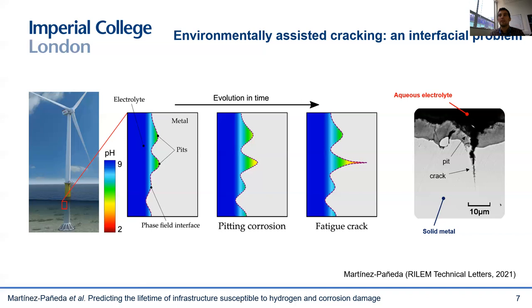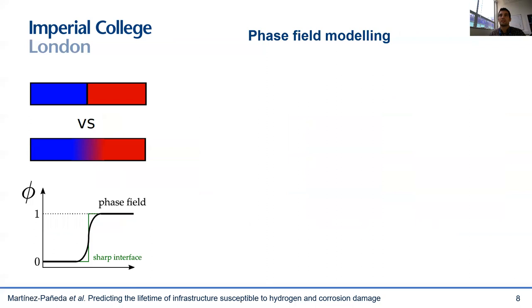The problem is that tracking evolving interfaces is a well-known mathematical and computational challenge. The good news is that a paradigm has been proposed that makes the tracking of interfaces an easy task. This is the so-called phase field method, which goes back all the way to van der Waals, but only recently has really taken off with the help of computers. Mathematically, we have two ways of dealing with interfaces: treating the interface as a surface without thickness, or using an auxiliary phase field variable that tells us where the interface lies.